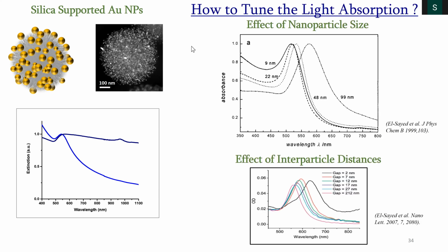So there are two ways one can tune the light absorption behavior of these gold particles. One is by simply changing the size. But you see now when I move from 9 nanometer to 22 to 48 to 99, what is happening? The lambda max is changing. It's not becoming broad, but shifting from one wavelength to another because of the size and the electron cloud.